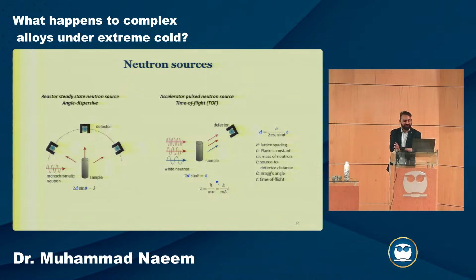So ultimately you can convert it by using this, Planck's constant, this is momentum, and ultimately, m is the mass of the neutron, and L is the distance from the sample to the detector, like how long it takes for the neutron after diffraction or scattering to reach your detector. And this is the equation which ultimately you use. The main thing is still the same: we're after d-spacing, but in this case we deduce that from the time of flight, which is t over here.